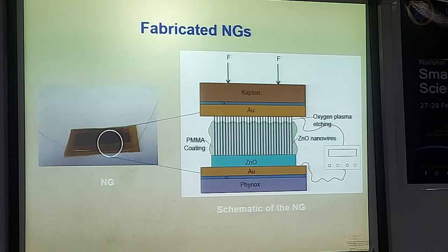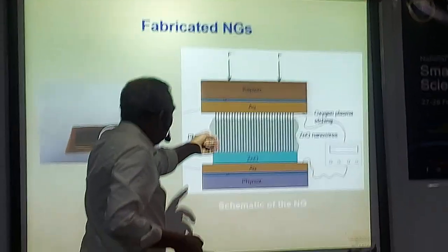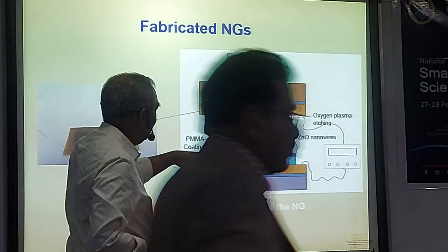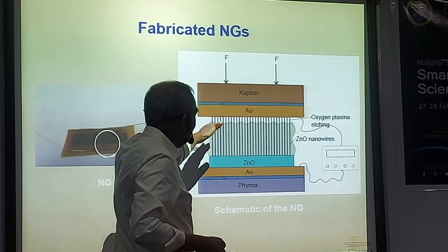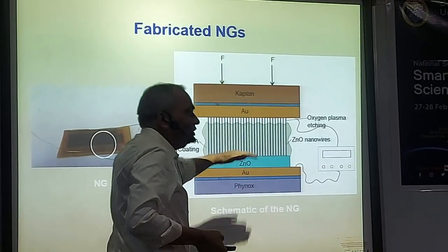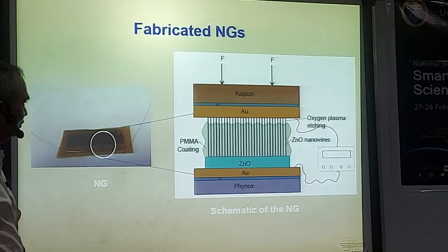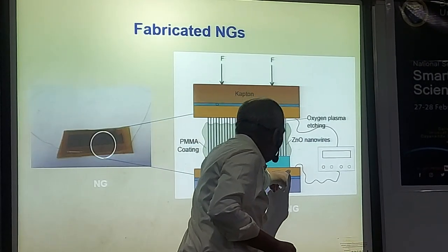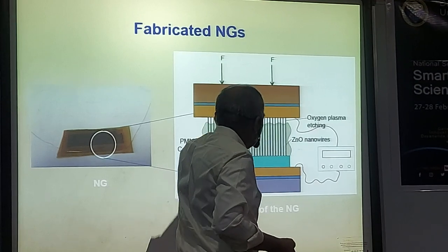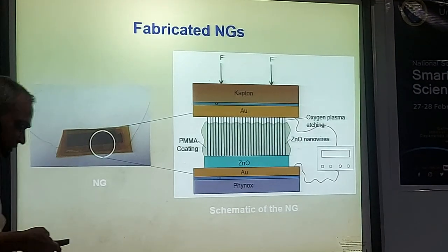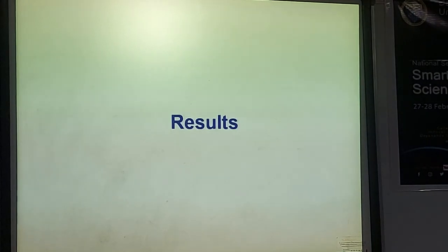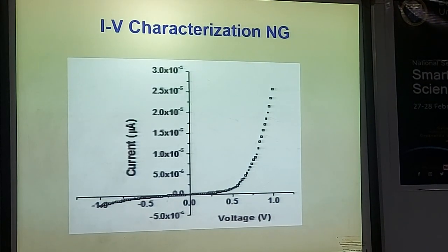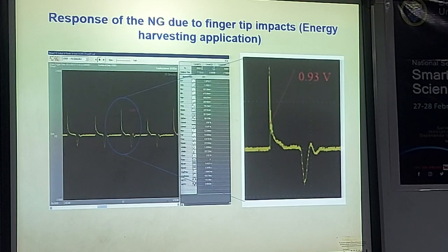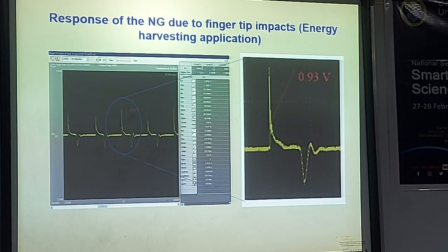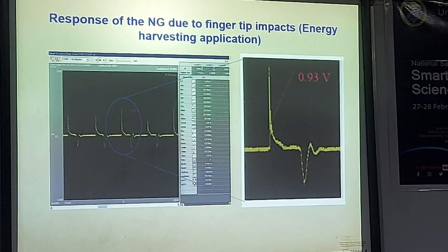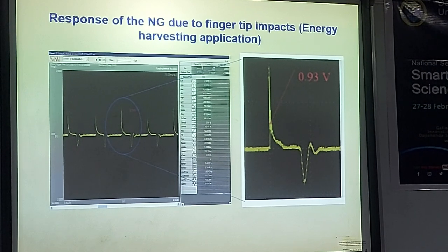So these are the zinc oxide nanorods. On the top side, we removed the PMMA by dry etching. And again, we pressed a Kapton layer and deposited the gold to form a nanogenerator. So we took one lead from the bottom gold electrode and one from the top, and then we realized the nanogenerator. These are some of the results that we got. When we subjected it to repeated impacts, this is the signal that we got. Maximum we could get about 0.93 volts.